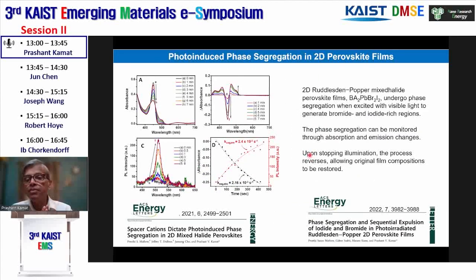We wanted to see whether even 2D mixed halide perovskites undergo phase segregation. And to our surprise, they do, especially if you have butyl ammonium lead bromide iodide, it is more facile. It depends upon the spacer cation. The organic core of the spacer cation suppresses this process, whereas if you have an alkyl chain, it's more prominent. So here you can see the n equal to 1 absorption peak going down when you shine the steady state light. And this is the difference absorption spectrum showing the formation of bromide and iodide regions. Again, what I also see is the emission.